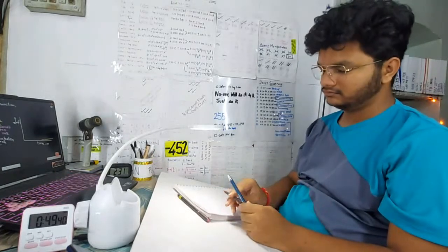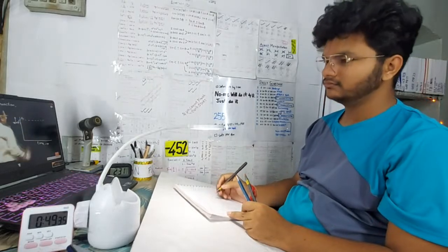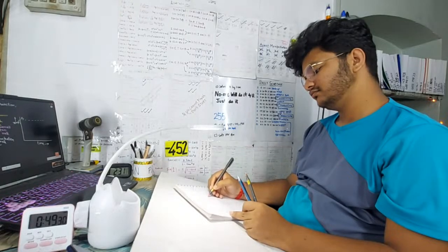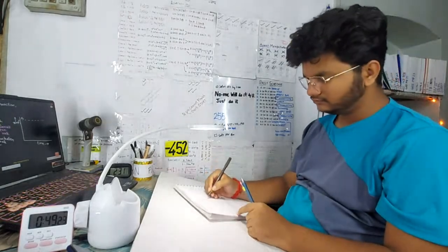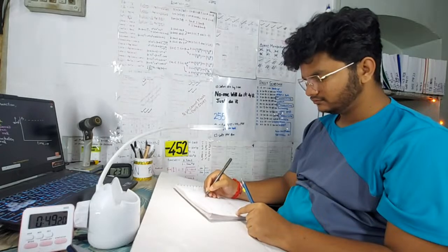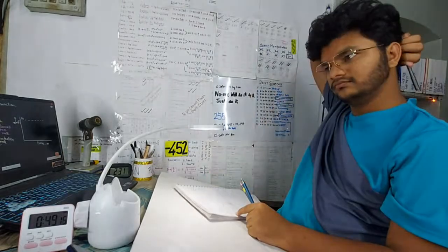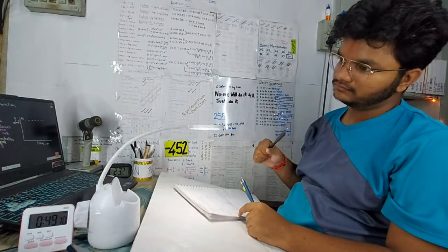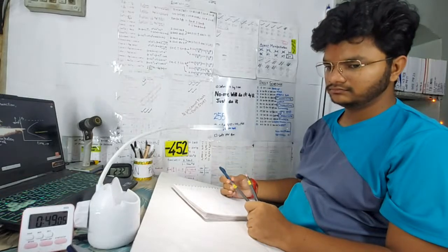Now let us see which change comes. Say for example, if this line is taken as the A1 line, as the reference line. I am talking about the overall transformation rate. Overall transformation rate initially increased and then decreased. But what is rate? Rate means 1 by time. So 1 by time has initially increased and then decreased. So then what will happen to time? If 1 by time is initially increased and then decreased, then what will happen to time? It will be reversed. Initially it will decrease, later it will increase. That means this graph should come like this. Right? This is the one which belongs to overall transformation.